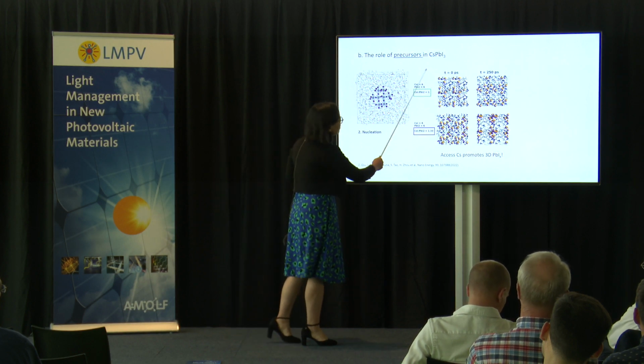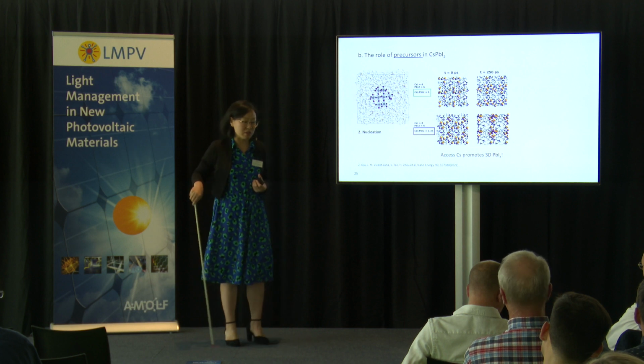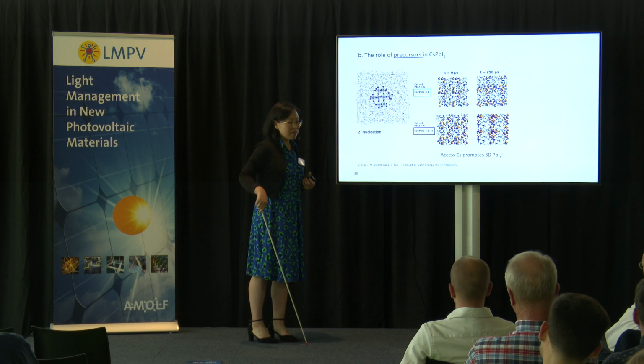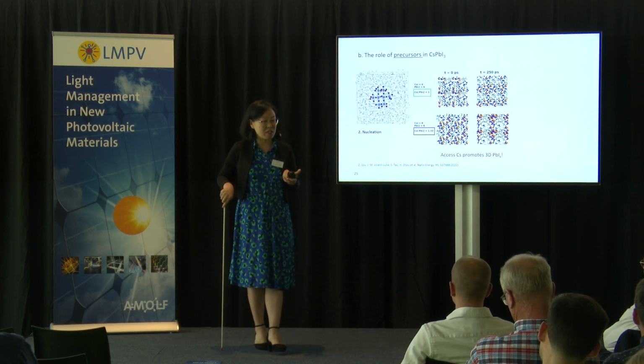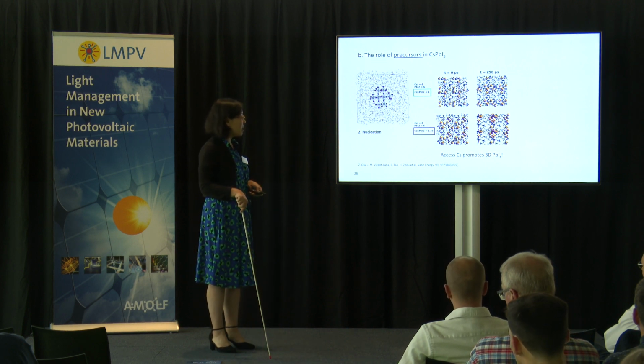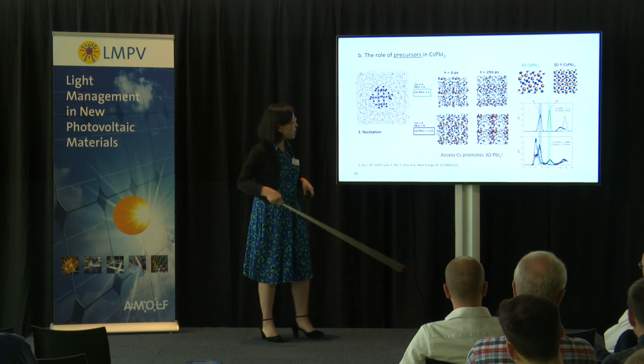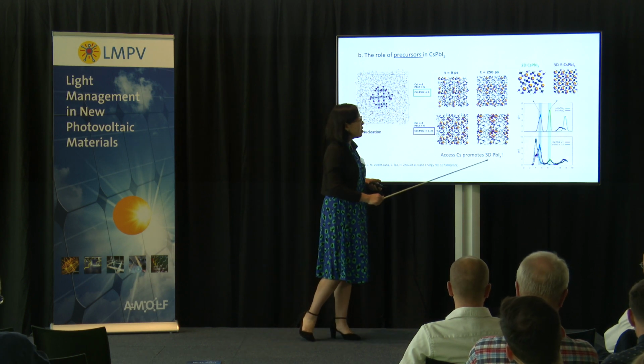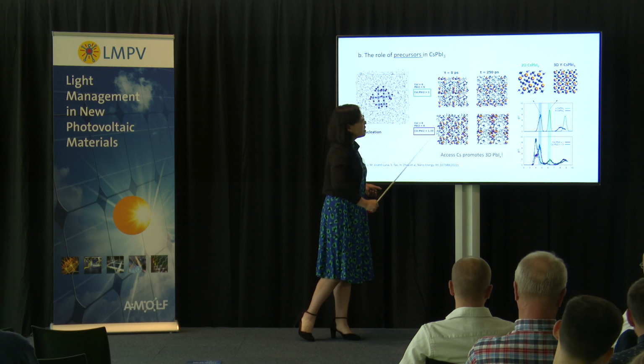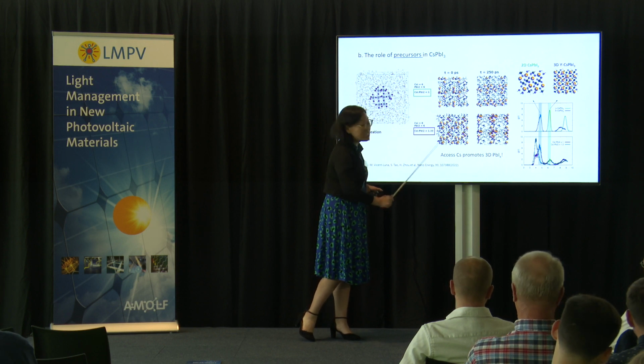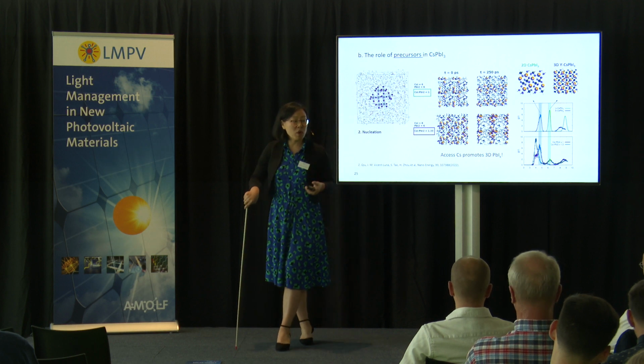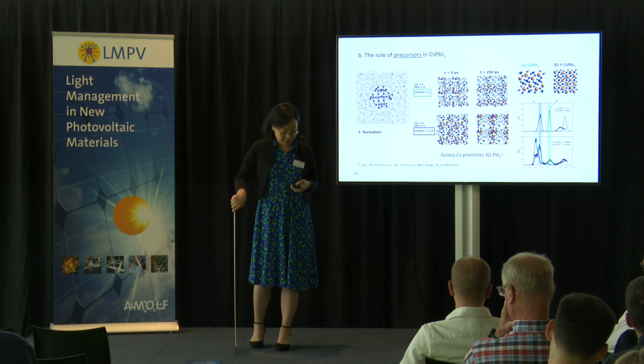So the second small example is in the cesium lead iodide, where we play with the precursor ratios. If we make the precursor a little bit cesium rich, we actually tend to get a black phase film that is good for solar cells. And what is happening there, if we do the simulation, this atom soup is a little difficult to read, but you will notice something. If we plot the RDF, you notice a little bit of cesium is very helpful to form 3D-like nucleation. And this promotes the growth of the black film.